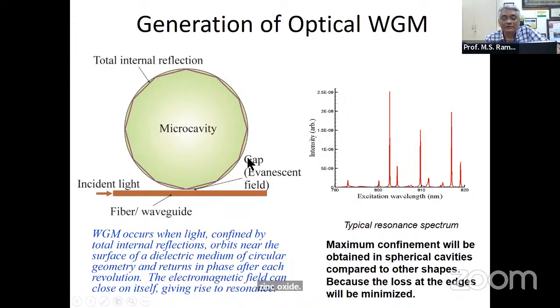Whispering gallery modes occur when light is shone on these micro cavities - the light starts orbiting near the surface of this dielectric medium, and then as it returns in phase after several revolutions, at a certain point resonance occurs. That resonance shows up as a strong emission at a particular wavelength, or it can happen at several wavelengths.